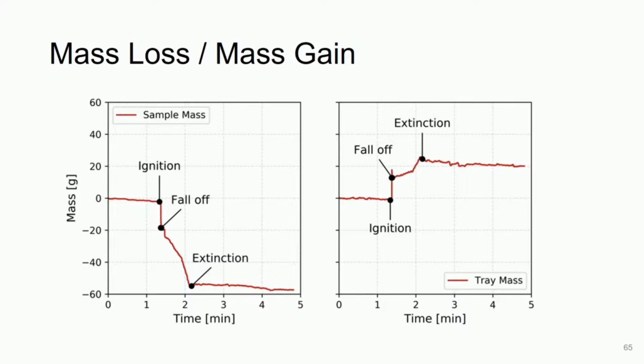There's a corresponding increase in the mass of the debris tray at the same moment that you can see, and there's a gradual sample mass loss that follows this loss of the aluminium plate, and that's associated with both burning and dripping of the polyethylene core material. During this period, the debris tray gains mass due to dripping. However, all of the mass lost from the sample is not gained by the debris tray, and clearly this is because some of the polyethylene has been consumed by burning before it reaches the debris tray. Similar plots, again, were developed and compared for all Work Package 1 experiments.